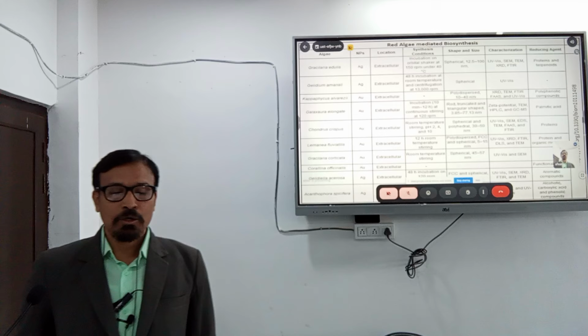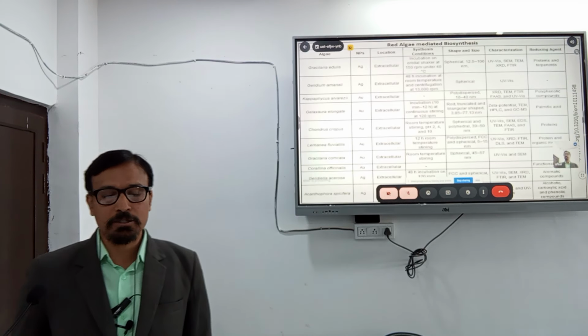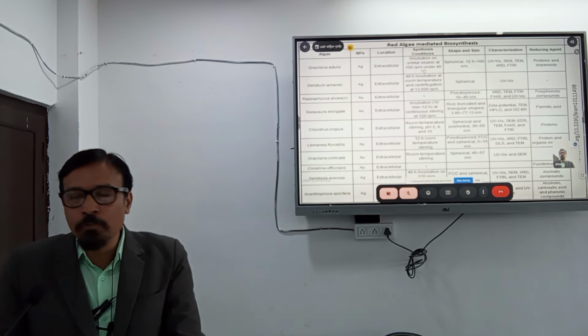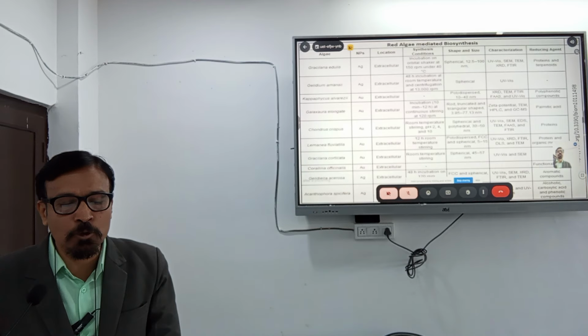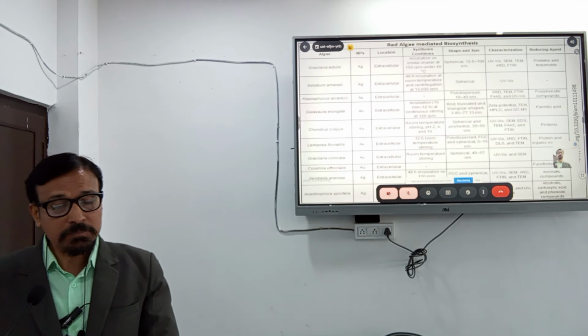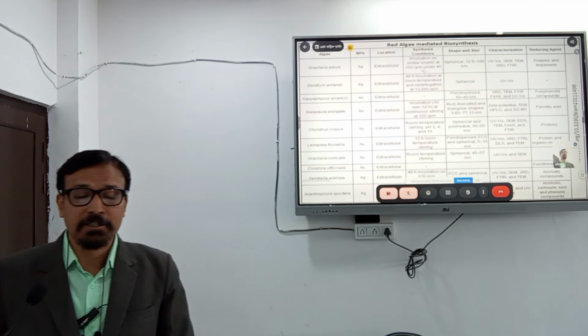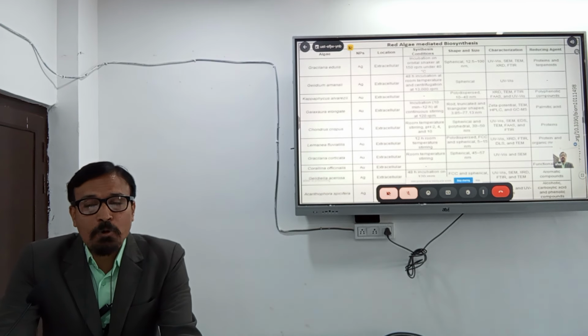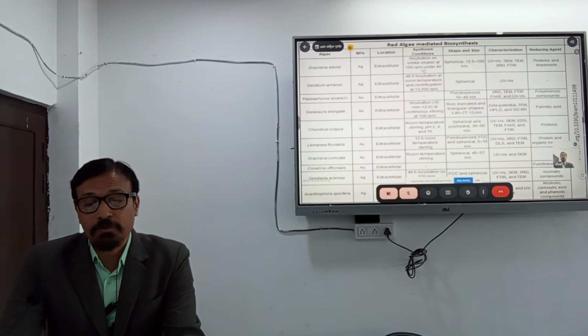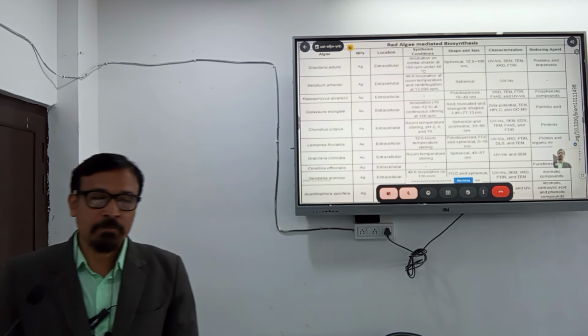And the Chondrus crispus, another algae with which we can synthesize these gold nanoparticles. The location is extracellular, and room temperature is sufficient for this process, but stirring is required, and pH will be between 2.4 and 10. Okay. The spherical and polyhedral shaped nanoparticles can be synthesized with Chondrus crispus in the range of 30 to 50 nanometers.